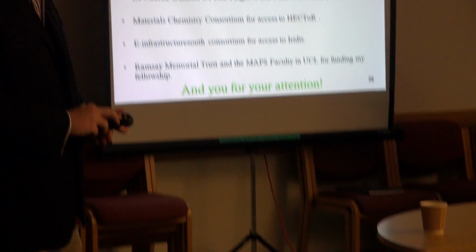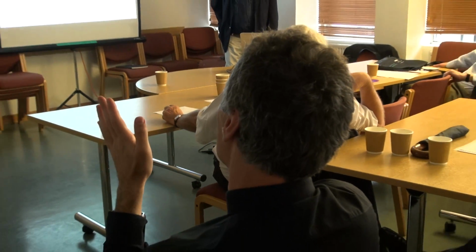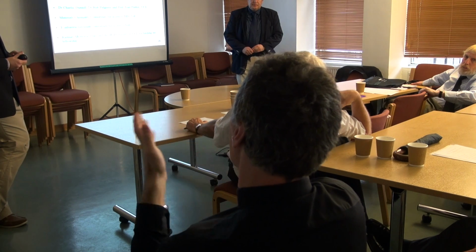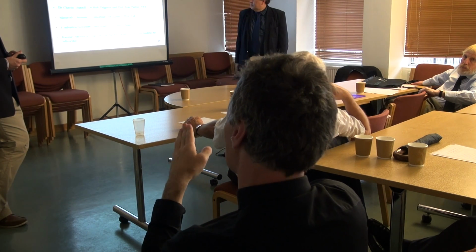I think it's very interesting, and I discussed it with Alexei before. There was one strange effect observed many years ago, that TiO2 exists in amorphous form, and its band gap is larger than rutile. Not anatase, but rutile. And this goes against any disorder models, right? Because it's supposed to be a lower band gap. So I think this is something very similar to what you're showing here. But I think your explanation about the maximum potential is very simple and very interesting.